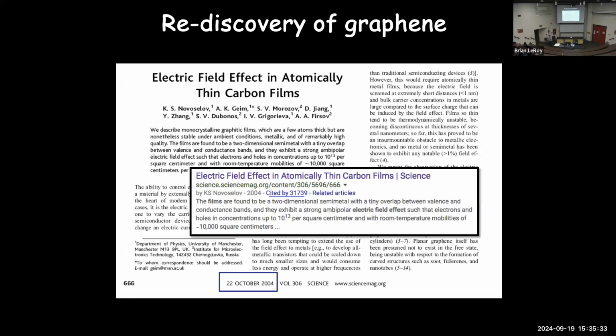And so the real difference here is the ability to isolate these materials and remove them from their substrates and allow us to then study the intrinsic properties of the two-dimensional material. The first one I talked about, the carbon film grown on a nickel surface, basically the electronic properties are still dominated by the nickel surface that's lying underneath it. And so even though you have made this two-dimensional material, which you expect to have interesting physics in it, you are basically dominated by the more boring, if you like, material that's underneath, the nickel substrate.